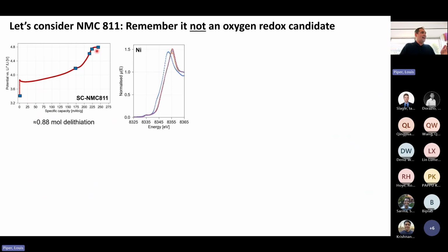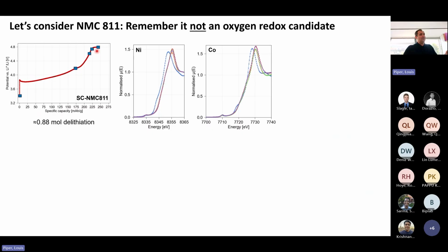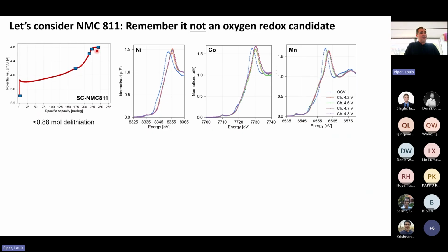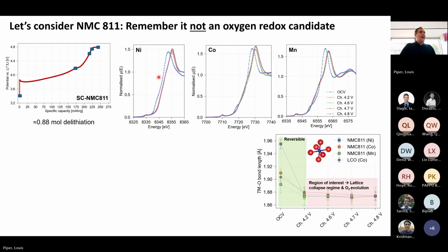We extracted both electrodes, prepared to show that everything behaves as we've seen before with other systems. We also did operando, where we did the pouch cells and looked at the XANES at the same time. And they both showed in that work that, yes, once you get to these high states, the nickel stops appearing to shift on the XANES, so it appears to stop oxidizing. The same with the cobalt. And then we did EXAFS at the same time.